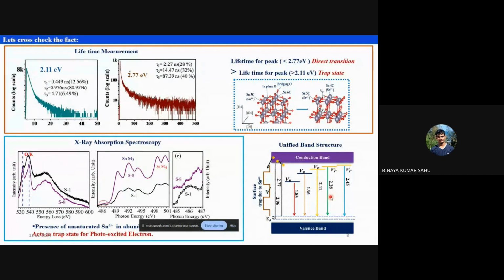Okay, so let me summarize whatever we have discussed yet. This is the tin oxide. There's a conduction band and a valence band. If you shine some laser, one hole and one electron will be created. And this particular electron will never come back to the valence band because of the dipole forbidden rule. However, this electron can go here and this will come here. So we can get some peaks at 2.45, 2.28, 2.11, 1.96 and 1.85 and all these things.